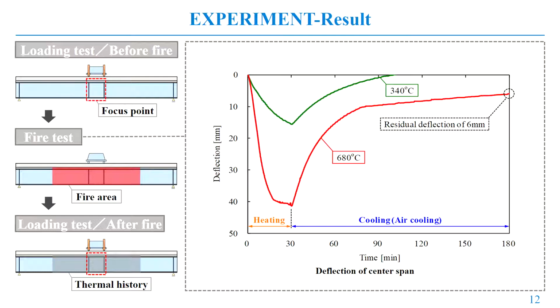This figure shows the deflection at the center of the span. The behavior in the fire shows a relationship between the vertical deflection at the center of the span and time. At 340 degrees Celsius, the deflection of the center of the span was 15 mm at 30 minutes. No residual deflection remained after fire. At 680 degrees Celsius, the deflection at the center of the span was 40 mm at 30 minutes. After fire test, a residual deflection of 6 mm remains.